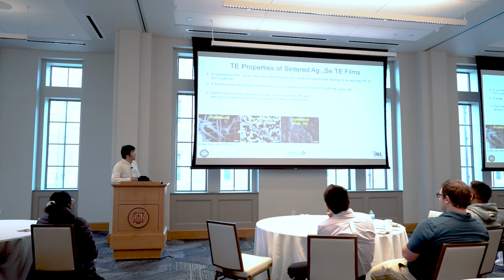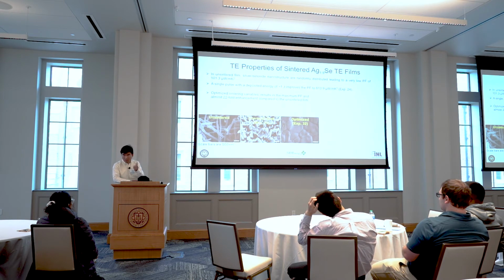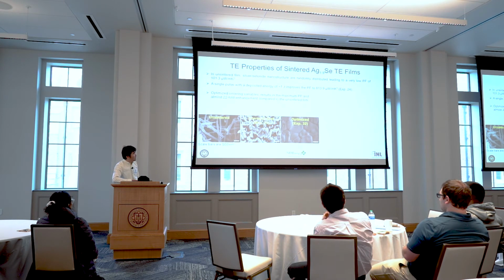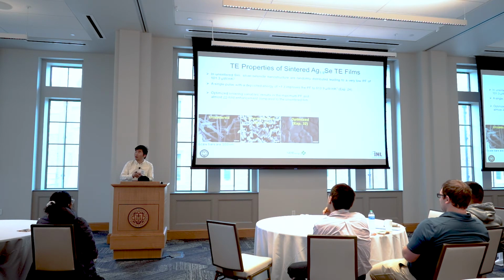Until the AI tells us to use a certain set of conditions: how many pulses, how powerful each pulse is, what the pulse duration is. That's a unique combination. And we're able to form a film that is much better than the original film. Like this is fully dense, and the boundaries are not very obvious. So this is good for charge transport and thermal transport.